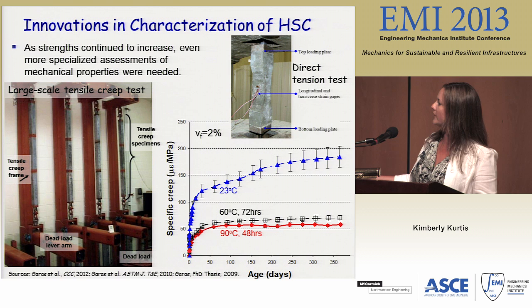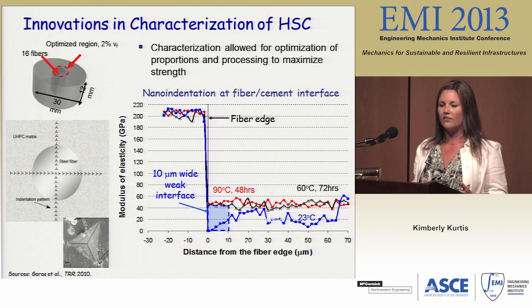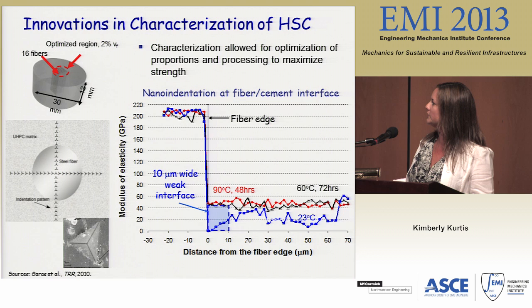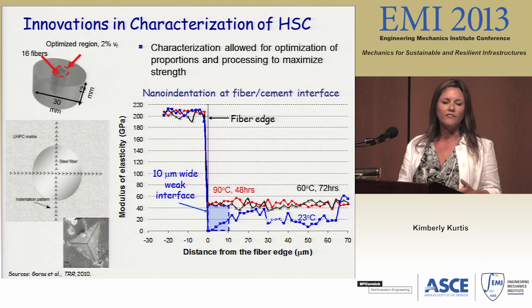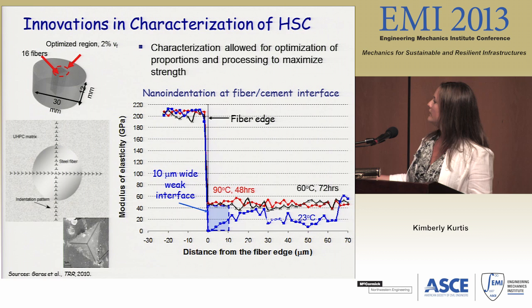Taking this down to a smaller scale, we also started harnessing advanced characterization methods like nano-indentation to better understand how mechanical properties are controlled by microstructure. In this example, we're looking at how we could potentially improve strength, durability, and stiffness by controlling defects at a fiber-cement paste interface. By doing heated curing, we can eliminate the lower modulus or weaker region that exists at that interface.